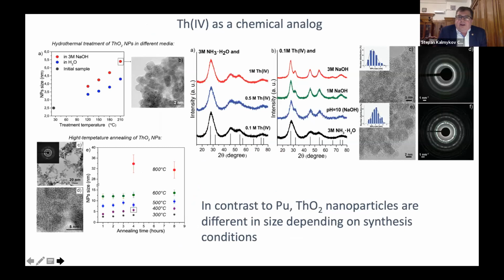Can we use thorium really as an analog to plutonium? Thorium has 0 electrons on the 5f orbitals, which means that any spectral changes that we can see are only due to the structural difference, and not due to the redox chemistry behind some processes. For thorium, we surprisingly found that depending on the concentration of the base solution, the concentration of thorium, and the temperature, we have various particles with different sizes.